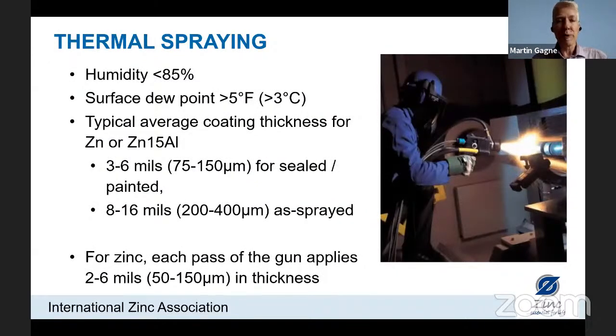Now we're ready to thermal spray. Again, we have very similar atmospheric conditions, humidity up to 85%, a surface dew point. Now, Graham had also mentioned duplex coating. So if we are just spraying zinc on the steel and we'll leave it, we want at least 200 microns of metal sprayed on the surface. But if we are going to seal that and paint it to make a duplex coating, we generally will put 100 microns of zinc, and then we will cover that with a paint top coat.